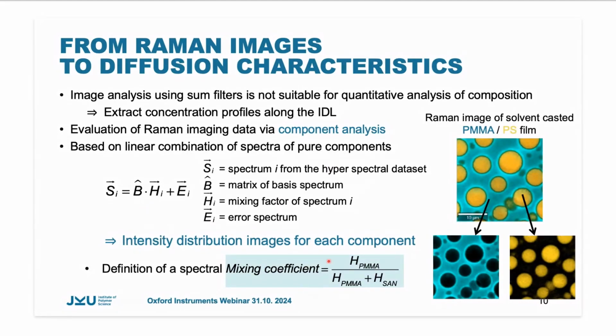What we are interested in is to get a little bit more quantification. Therefore, we assigned a mixing factor. So for each point in the spectrum, we want to have the mixing factor of the individual polymer in relation to the total mixing factors of both components. But this is not enough to get quantitative data which are relevant for chemists. We want to have weight percentages.